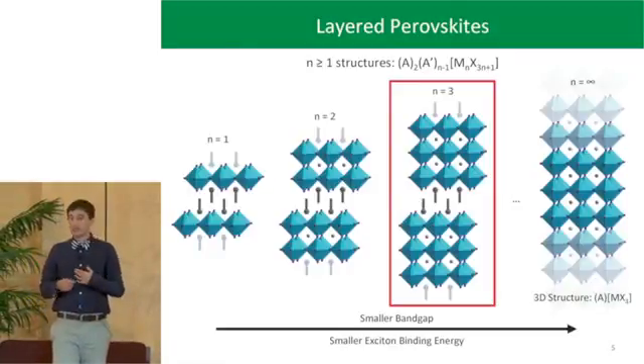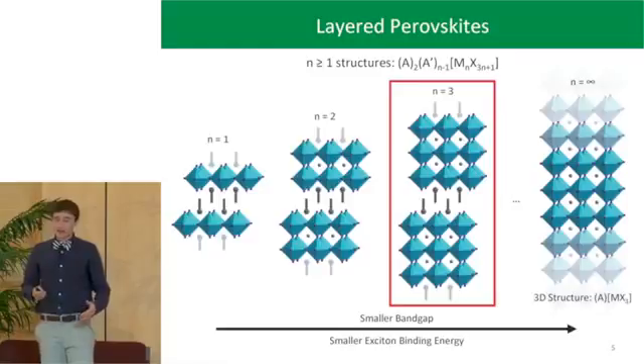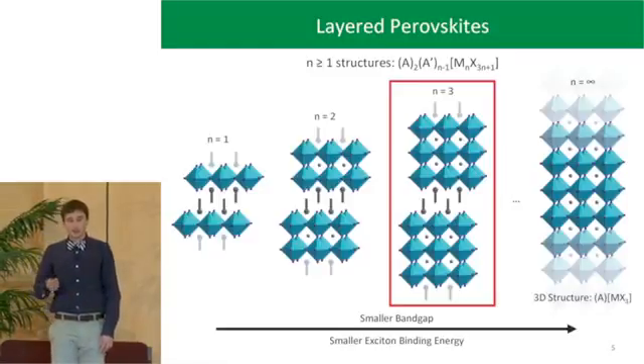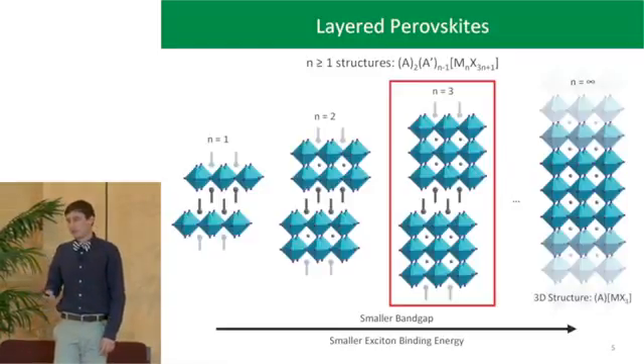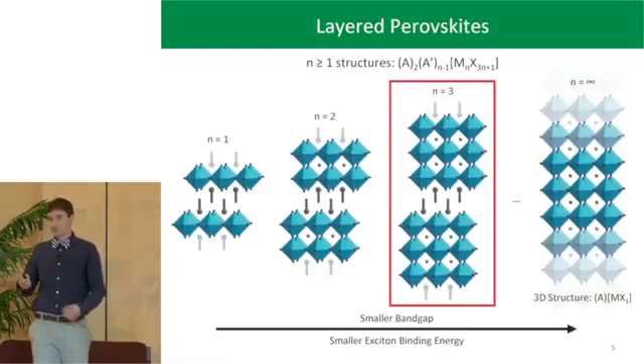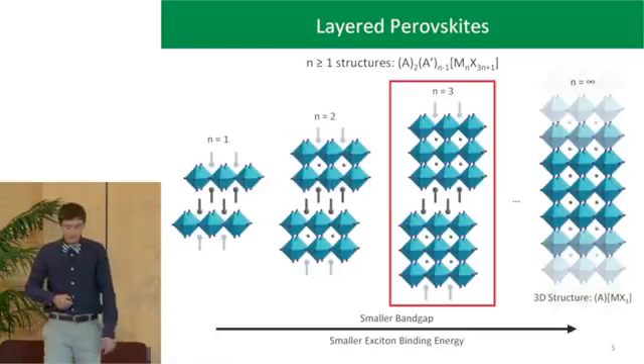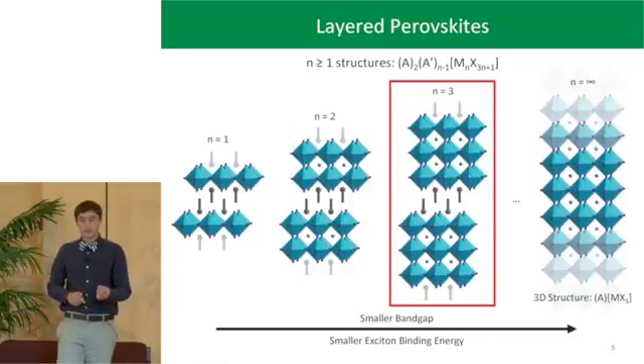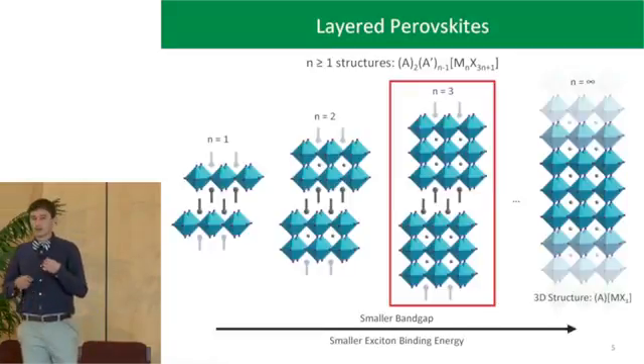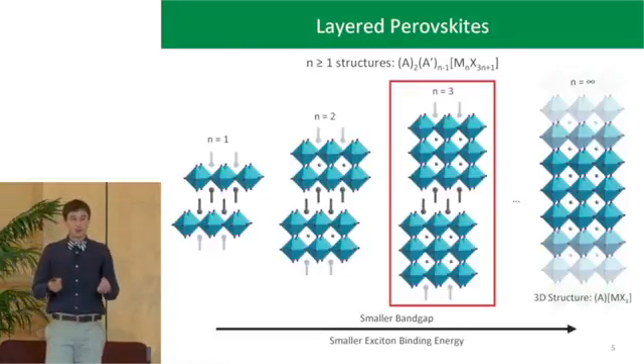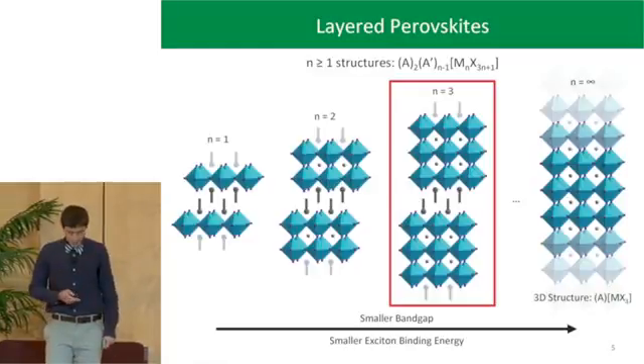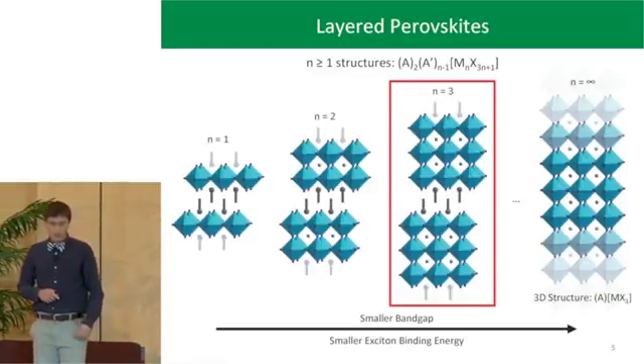And hypothetically, you could get any structure you wanted. In reality, it's pretty hard to get some of the ones with higher N values. But if you take this to the limit, you eventually get N equals infinity, which is actually just the three-dimensional structure that I talked about before. So these materials, the layered materials, are really nice because you're adding in this organic molecule. And you can imagine adding any functionality you wanted into that material just by using organic chemistry to put anything that fits inside of the structure. So the layered perovskites also tend to have different properties.